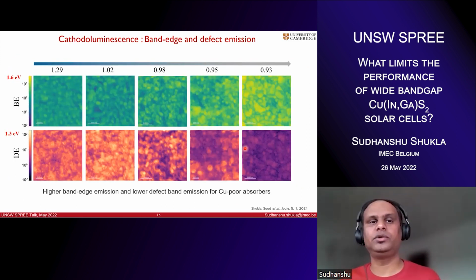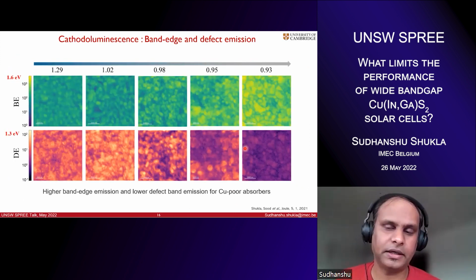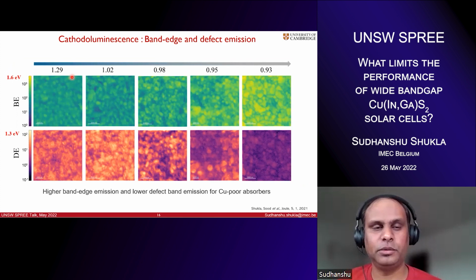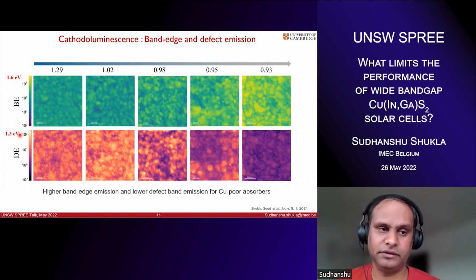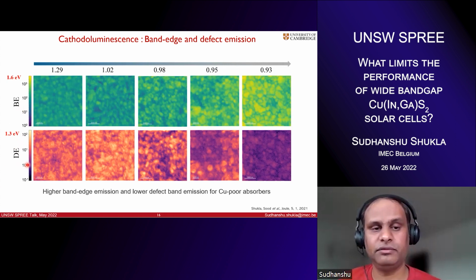Then we try to investigate how the spatial distribution of these defects is within the absorber. So there is some cathodoluminescence mapping that you are seeing in this slide. The top one is taken at 1.6 eV, which is the band edge emission, and the bottom one is the luminescence that you are seeing from 1.3 eV, which is the D1 defect that I showed previously. And what you notice here is that as you go more and more copper poor, the band edge emission increases. So you see the colors are more bright here, for example, and at the same time your defect band intensity decreases. So these plots appear more and more dark as you become more and more copper poor.